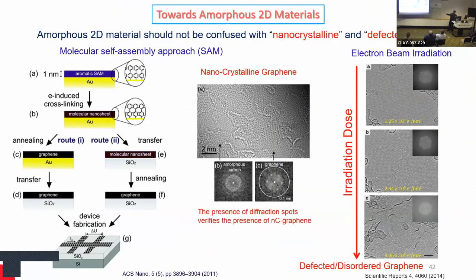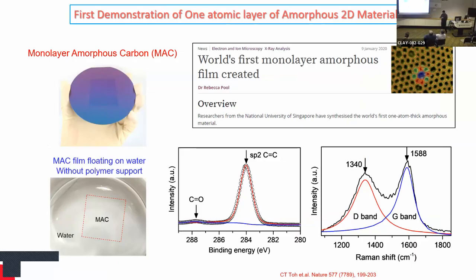There has been some work done previously to achieve amorphous materials, but they are not really amorphous. They are basically nanocrystalline. You also may have disordered or defected graphene when using these different techniques. But my group in Singapore achieved, for the first time, a freestanding, completely monolayer amorphous carbon. That was in 2020. It's completely sp2 carbon. It's not like 3D amorphous carbon, which is basically sp3 bonded. It is a single layer of sp2 bonded carbon and can be grown over a larger area. You can see this film floating on top of the water without any polymer support. Normally for graphene growth, you need support to transfer. So it's strong enough to sustain its structure.